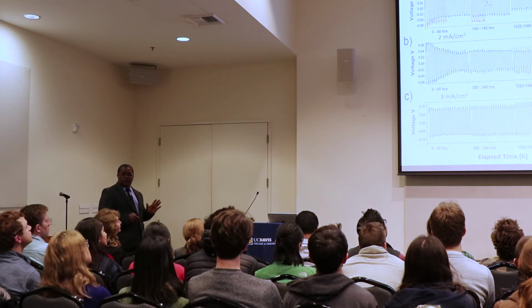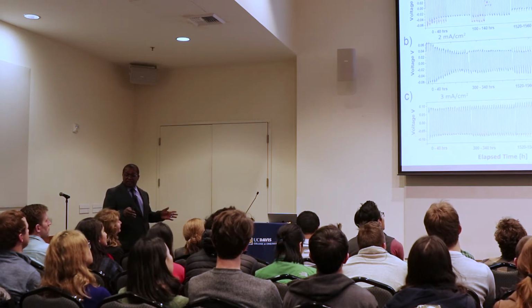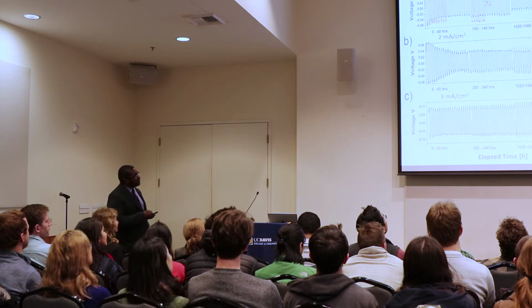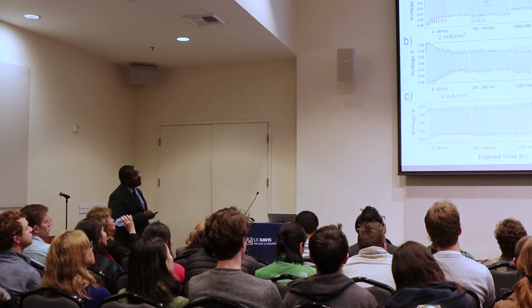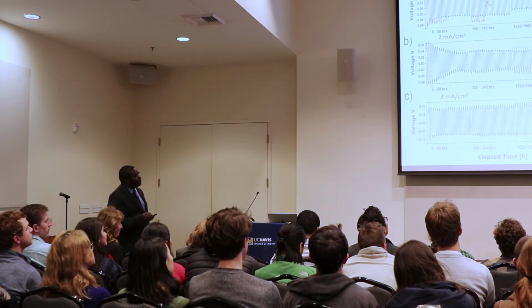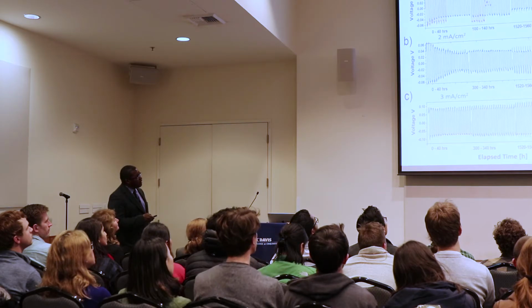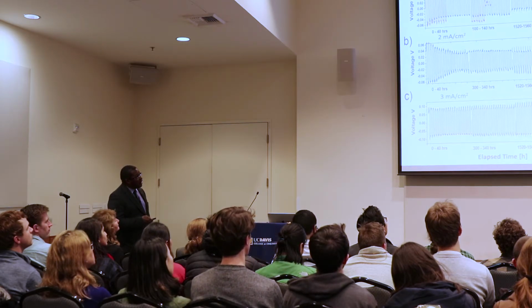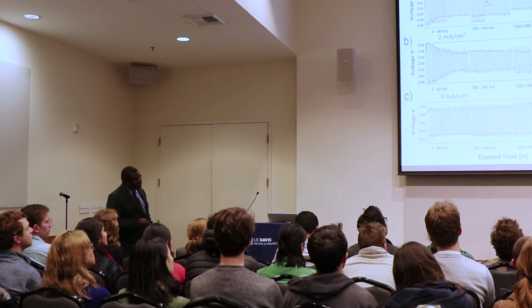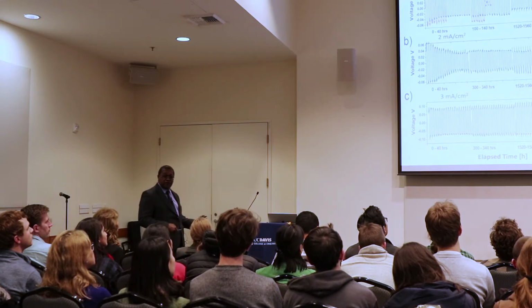One of the beautiful things about anodized alumina is that we can actually change the pore size, and that's what I'm showing here. For the highest current, here's what occurs as you change the pore size: 20 nanometers, things look good; 50, still good; 100, they get shaky; 200, a little bit shakier but still more or less stable; but by 300, everything falls apart.